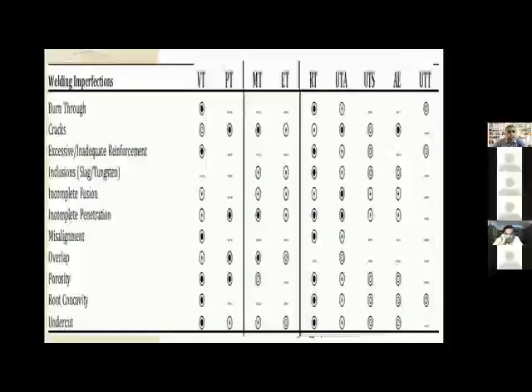So when I'm trying to detect a crack, the best method is not radiography testing. The best method is not UT shear wave testing. If it is on the surface, it is PT. If it is on the subsurface, it is MT. And the other way that you can find is using eddy current testing, where you have to use specialized electromagnetic probes on the OD of the shaft, and that will give you maximum probability of detecting such cracks.